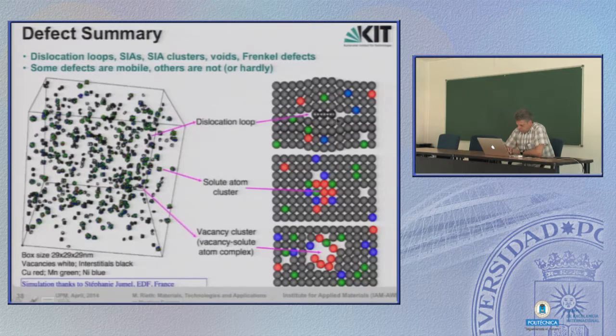This is how we can consider dislocation loops. If we have solute atoms in a real alloy, then not only self-interstitial atoms, but also these solute atoms can end up in interstitial locations, or they can form clusters. And also vacancies, as we have seen, can form big holes in the matrix, but they can also mix with the solute atoms. So a variety of defects are produced. Some are mobile and some are not so mobile. This is about what we will end up with after irradiation.